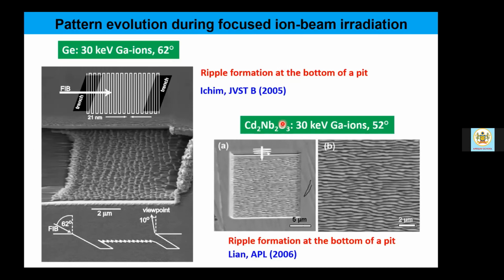I talked about focused ion beams. So these kind of patterns can be premeditated, patterns can be programmed, and the machine itself can follow that kind. I mean, produce these kind of patterns. That's very important. So here is an example of a material, a complex oxide, cadmium niobate, at an incident angle of 52 degrees, beautiful ripple patterns were observed. And using 30 kV gallium ions in germanium at an incident angle of 62 degrees, these kind of patterns were observed.